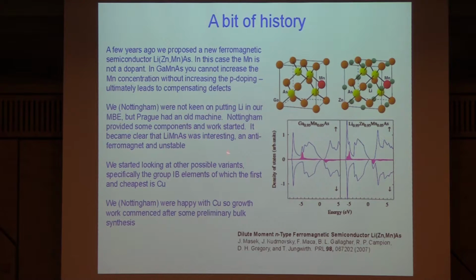In the end, it turned out actually that lithium manganese arsenide wanted to grow. It also turned out it was very interesting. It's an antiferromagnet, and of course there was interest by that time, lots of interest in antiferromagnets, so we thought, hey, we've got an antiferromagnet. Unfortunately, it was also chemically unstable. So I was getting a bit bored in Nottingham, and I wanted to do something, and so we started looking around for alternatives, and we started thinking about the 1B group, the copper, silver, gold.